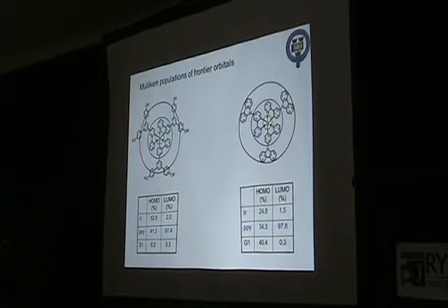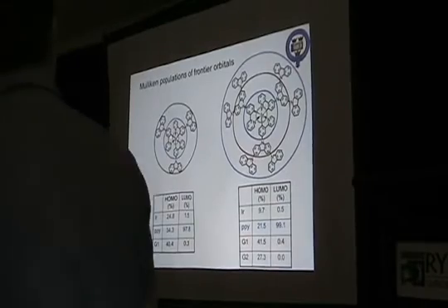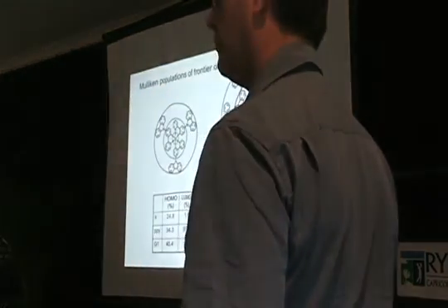And so we've redistributed the highest occupied molecular orbitals in terms of where they are on the complex. If we go from the first generation to the second generation, we still see a significant amount of HOMO density on the outer carbazoles. And what's happening effectively is we're bleeding it away from the iridium complex at its core.